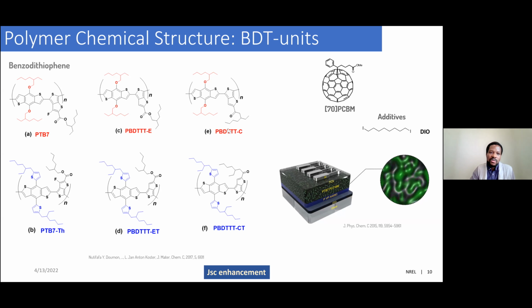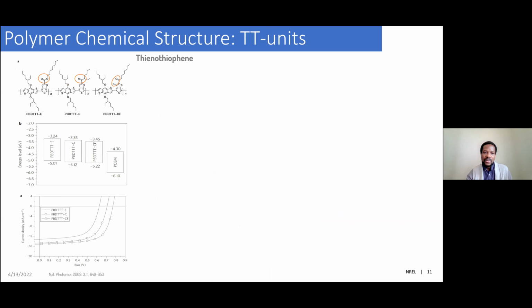And when you move from the 1D to the 2D polymer, or the red polymer to the blue polymer, in a blend with PC70BM, you begin to approach 10%, which is very good news for the community. Now, as I said, we can look at these polymers in two ways. If you look at the first polymers, the trick played by Hou et al. in those days, if you look at the TT unit, so now we move from the BDT unit to the TT unit, you can see that they begin to play with a substitution.